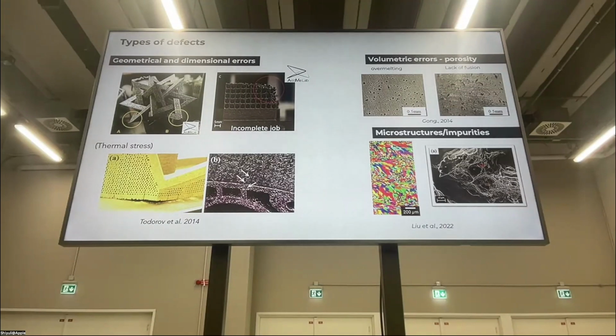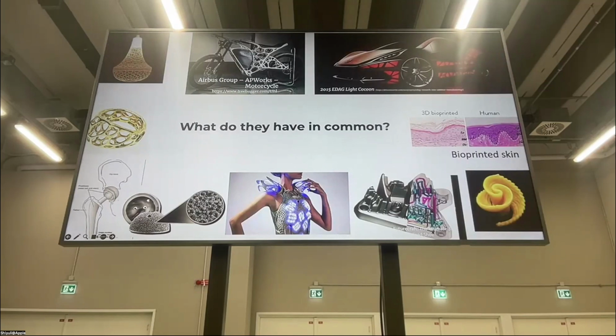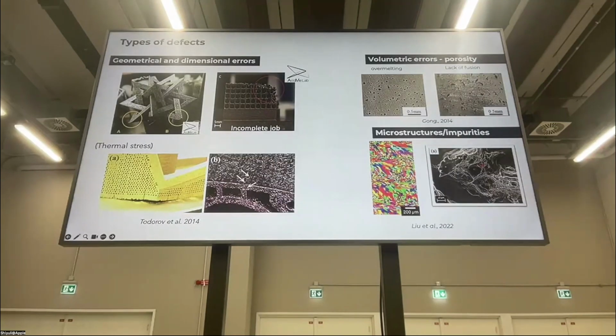We have been spending most of our effort in the last years trying to avoid, basically, defects. And these are a lot of defects that can arise in parts. Since, as I was just showing, all these parts have complex shapes, this is what is really a common point in all parts that are 3D printed. Unfortunately, complexity means that you can have a lot of defects, which are geometrical and dimensional defects. You can have even small cracks or some sort of thermal stress that are creating some change of the final shape. Unfortunately, you can have even small defects inside the part that are called porosity, due to excessive melting or insufficient energy while we're melting. And these are unfortunately a big enemy of the mechanical performances at the end.